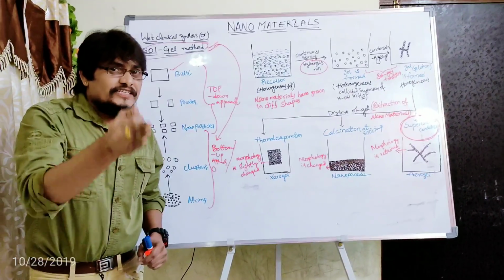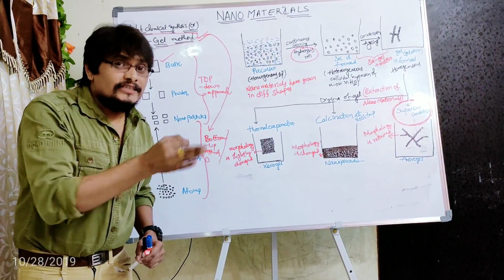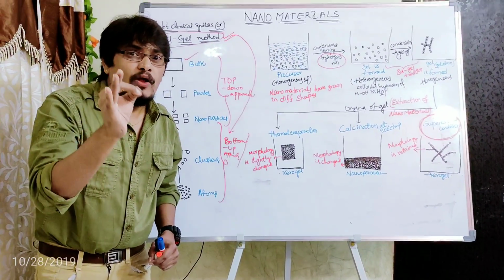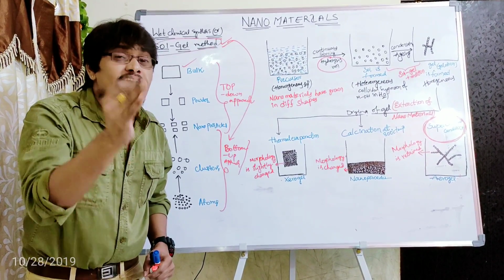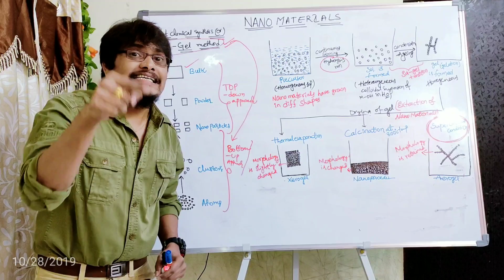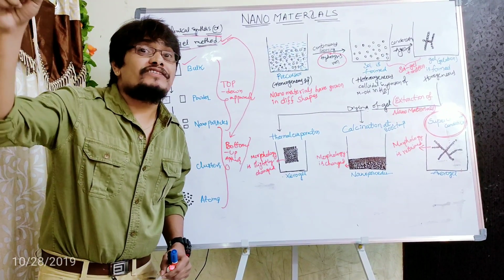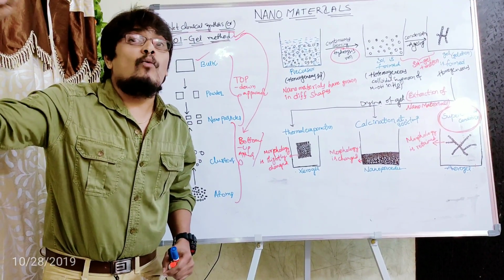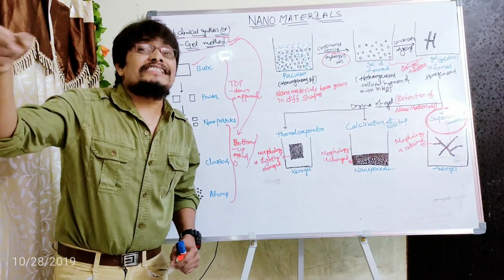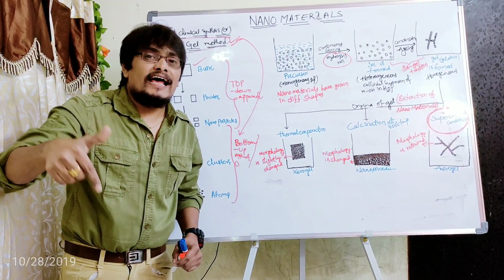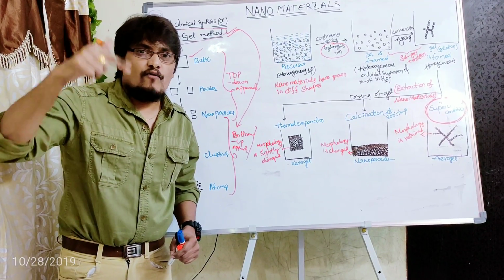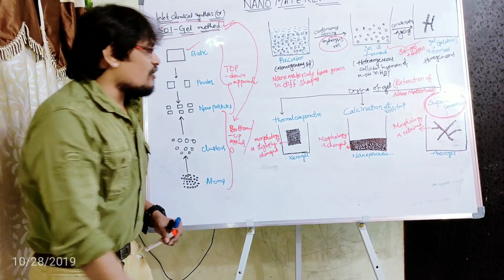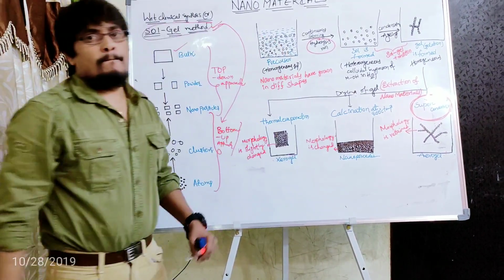Now what is the substance which is being heated here? The nano-sized metal oxide. Whenever the nano-sized metal oxide which is a part of the gel which is along with the alcohol is heated at the temperature range of 600 to 800 degrees centigrade, whatever the alcohol content which is impregnated inside the nano-sized metal oxide gets evaporated, resulting in the formation of nanopowder.